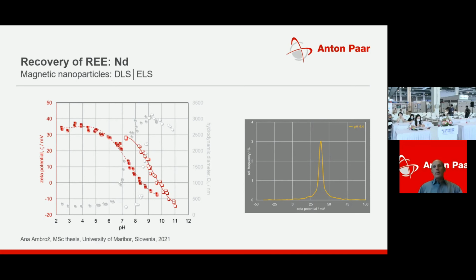As for the particle size, the evolution of the zeta potential with pH is also almost reversible and shows similar hysteresis to that observed for the hydrodynamic diameter. We finally conclude that the exposure of these magnetic nanoparticles to alkaline conditions somehow affects the amine functional groups to a certain extent.